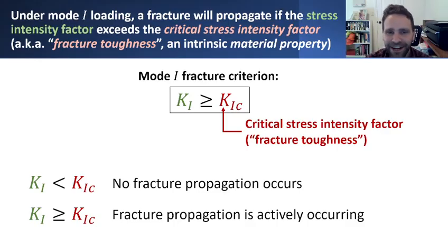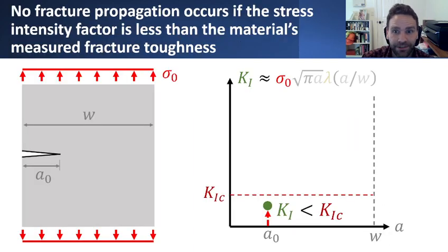Now, this fracture criterion allows actually for the mode 1 stress intensity factor, K1, to potentially exceed this critical value. And what happens if it exceeds it, or is at least equal to it, dictates various other things pertinent to assessing whether the crack growth itself is stable or unstable. And to really understand what that distinction means, stable versus unstable crack growth, it's useful to look at a particular